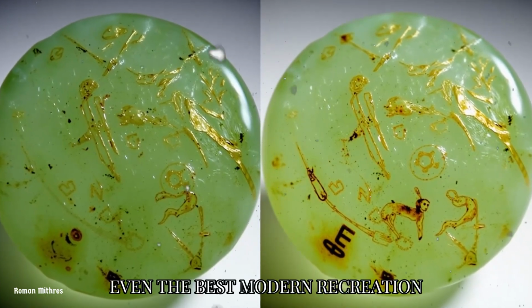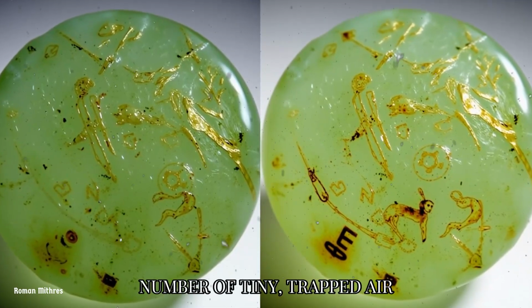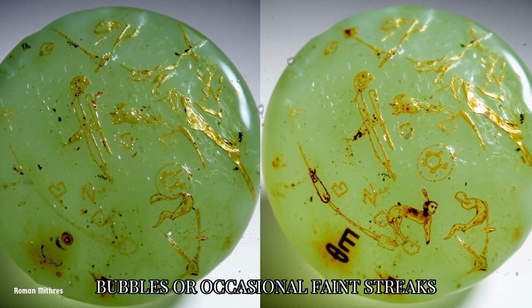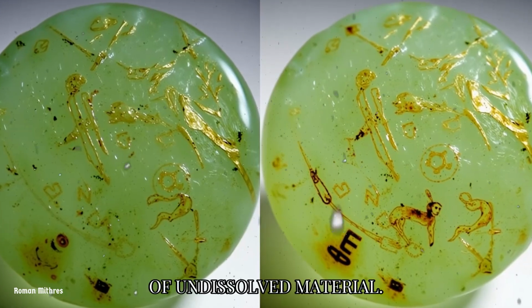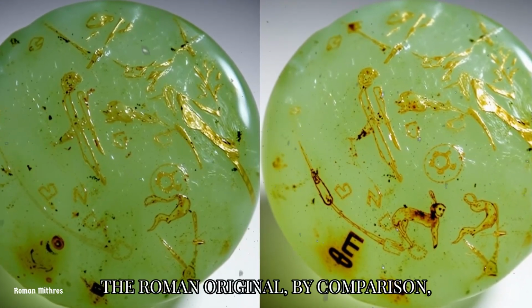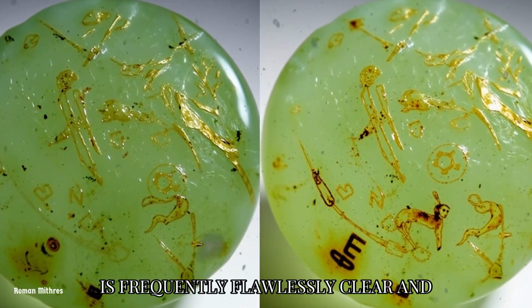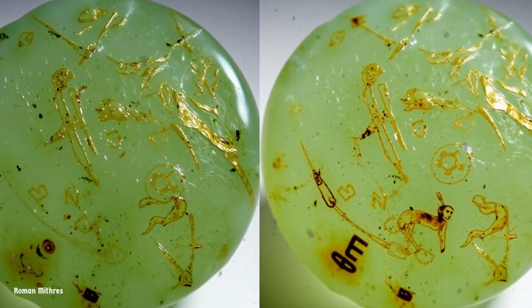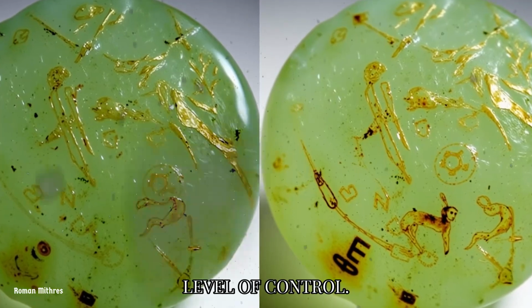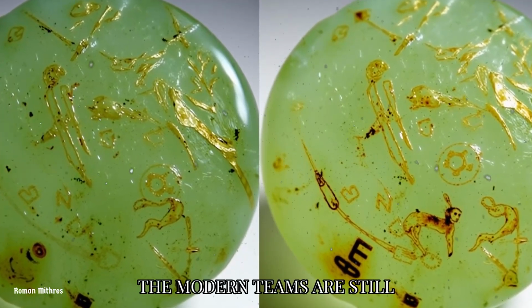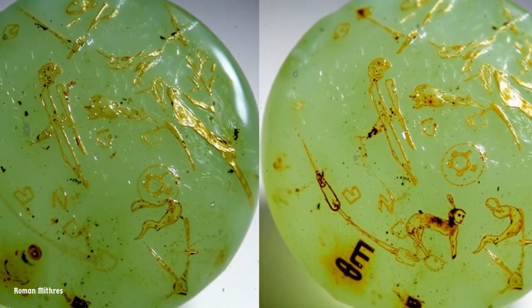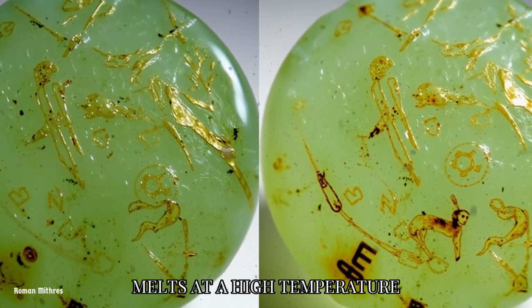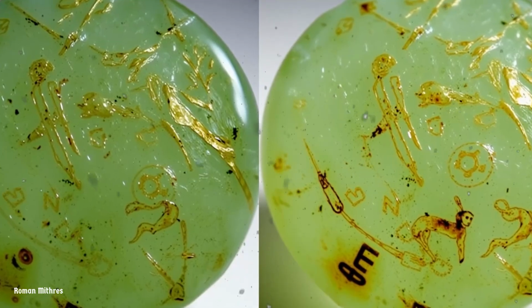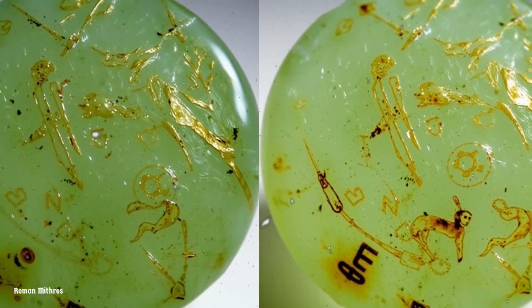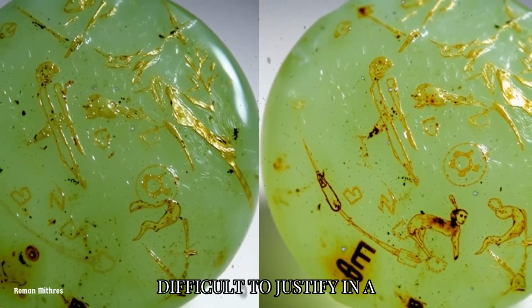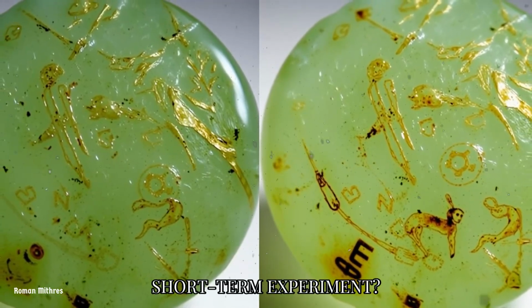Even the best modern recreation often has a slightly higher number of tiny, trapped air bubbles or occasional faint streaks of undissolved material. The Roman original, by comparison, is frequently flawlessly clear and homogeneous. This speaks volumes about a level of control the modern teams are still struggling to achieve. Did the Romans hold their melts at a high temperature for a day or more, practicing a level of patience and fuel consumption that is difficult to justify in a short-term experiment?